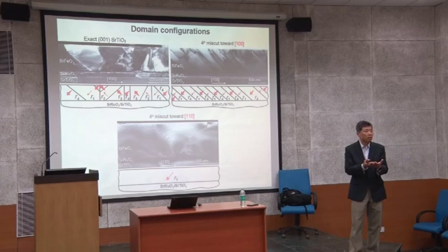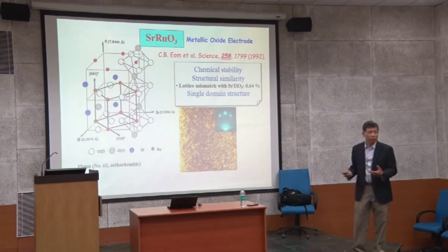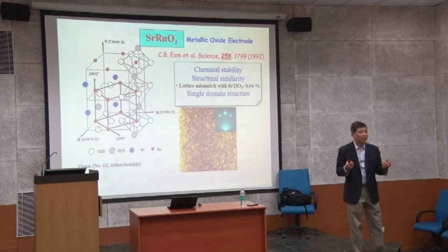So for example, strontium ruthenate, as I mentioned earlier. If you use an orthorhombic substrate, like scandate or neodymium gallate, a type of orthorhombic substrate with the same kind of space group, then you don't have to do miscut. You just grow it, you grow monodomain. A perfect monodomain forms on top of those things. But with miscut, your lattice mismatch is bigger. So that's why with strontium ruthenate and neodymium gallate, the lattice mismatch is huge, even though it's an orthorhombic substrate with the same symmetry.